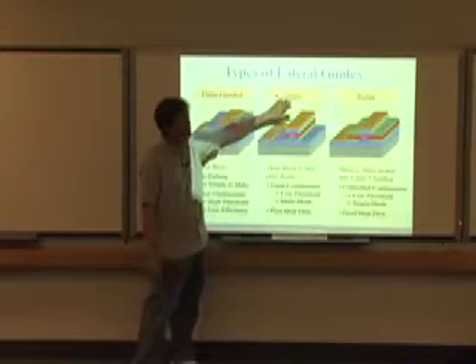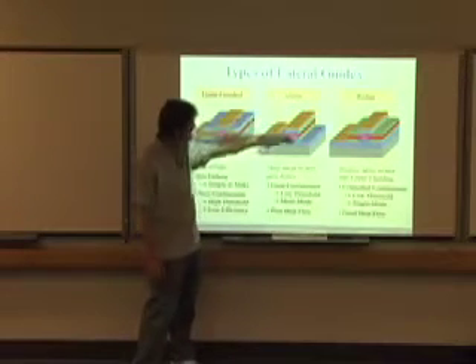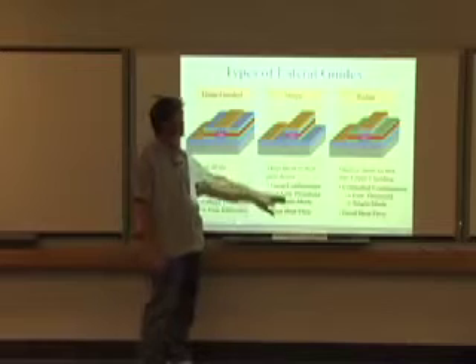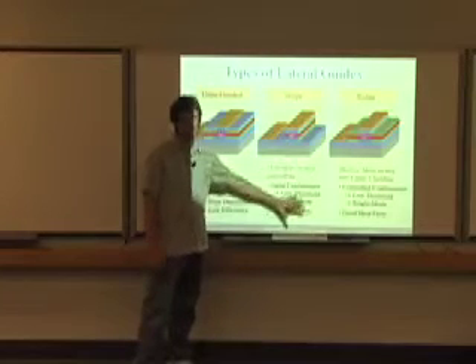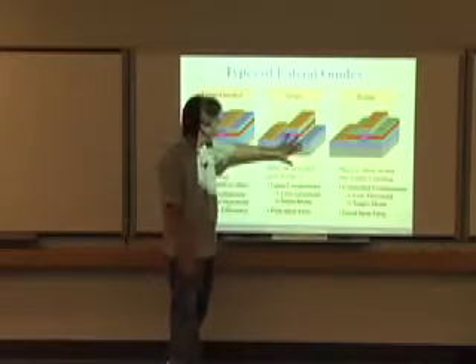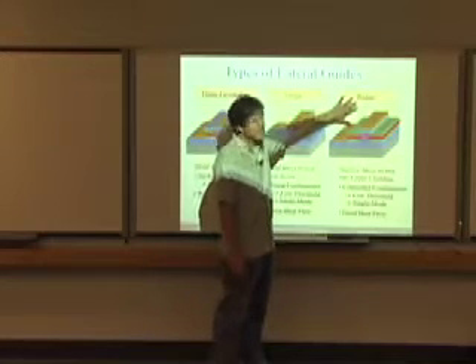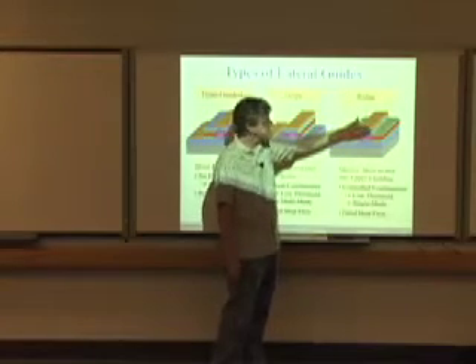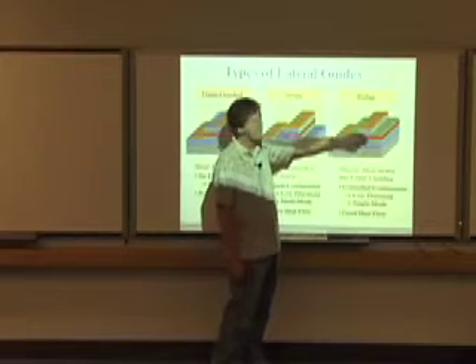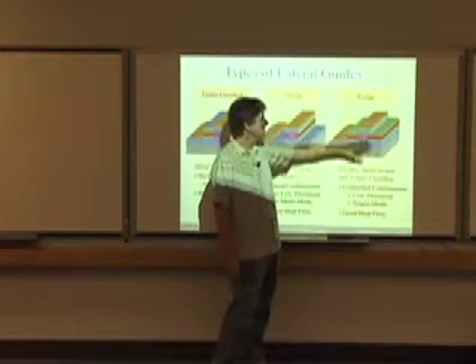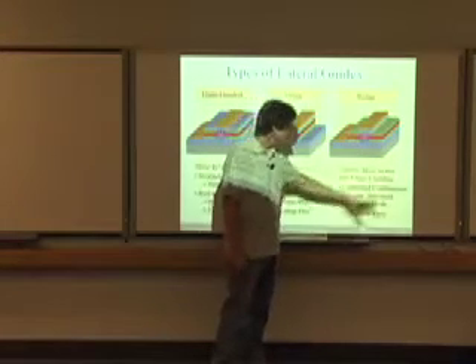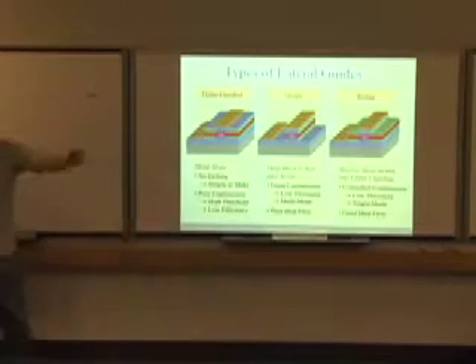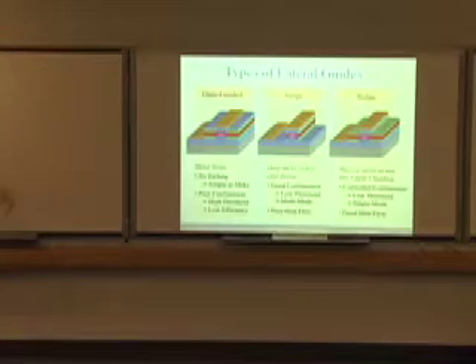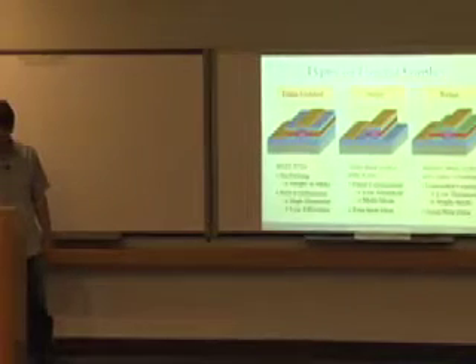And if you go with a striped structure, which I think Nakamura started out with, a deep mesa structure, it has good confinement, low threshold, but it's multi-mode, and it has poor heat flow, so not the best for CW. The ridge structure is kind of the ideal case, because you can just etch down through some of the P material. You can get good confinement of the current. You also get good optical confinement, and it's really the best situation. You get good heat flow. And this is what Nakamura ended up using later on for some of his better devices. Not that the first ones weren't good.